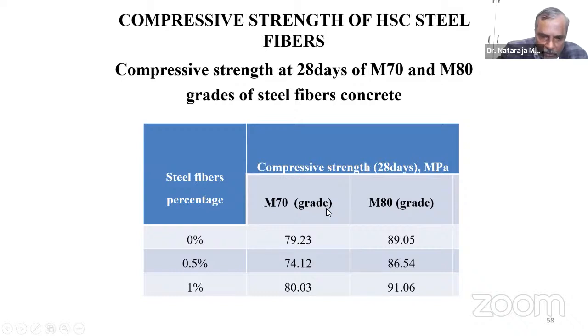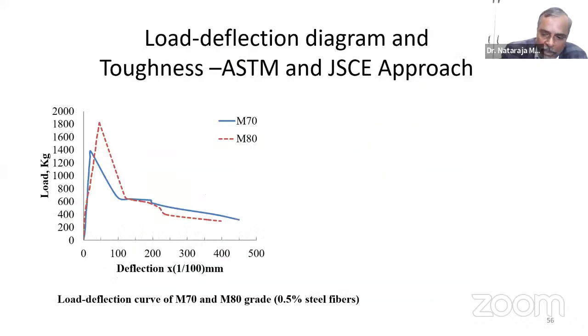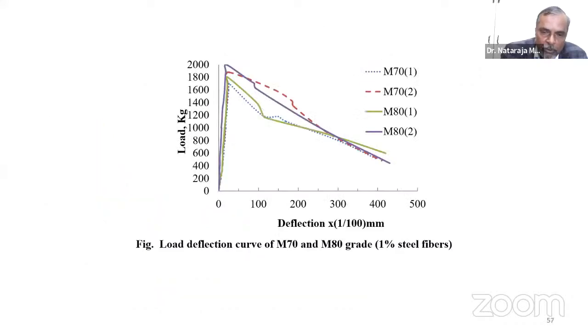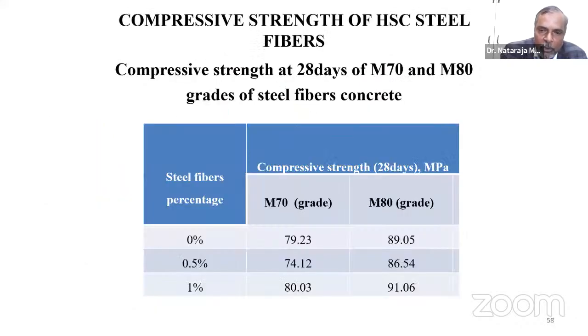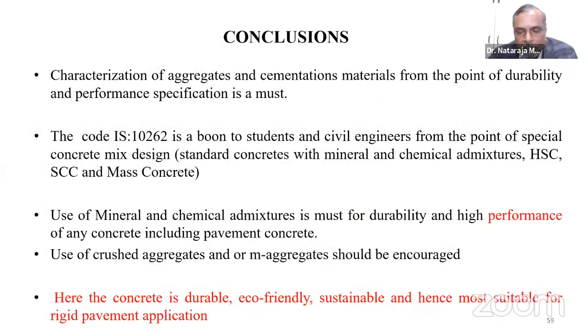And as I mentioned, kindly see the increase in compressive strength. In fact, the compressive strength is decreasing marginally for 0.5%. For 1%, a small percentage of increase. What it means, the addition of steel fiber need not increase the compressive strength. It can increase marginally, sometimes it can decrease, but mind you, that is not the idea. The idea is only to increase the area under the curve, unless these things are looked at from the point of mix design. So there's no point in you simply adding the fibers.